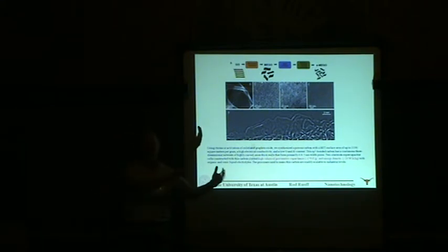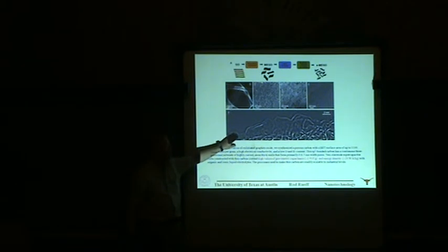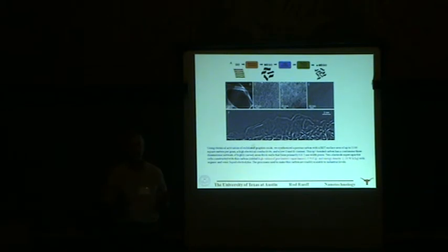So larger than the 2,600 number that I told you before for graphite. It turns out that the electron microscopy done by Eric Stach at Brookhaven National Lab shows that this entire material, everywhere he looks, consists of one atom thick walls, but now distributed in three-dimensional space. And electron energy loss spectroscopy and XPS by colleagues shows that it's all sp2 bonded carbon. There's no sp3 bonded carbon in it. There's very little hydrogen and essentially no oxygen. It seems to be pure carbon.